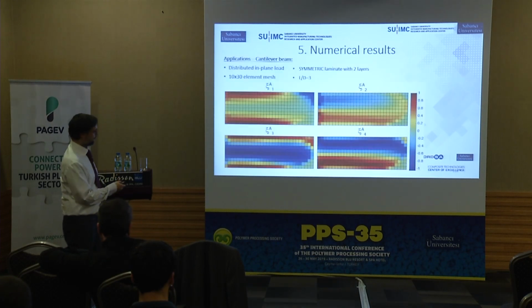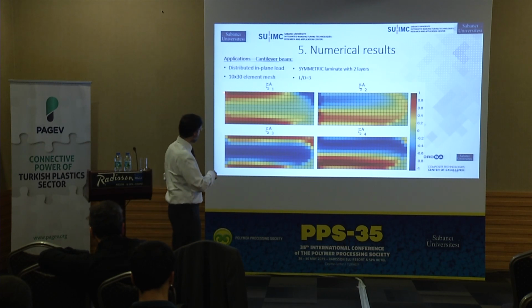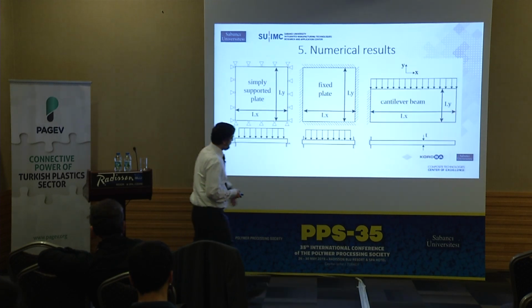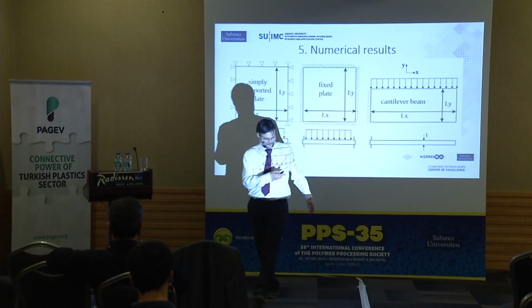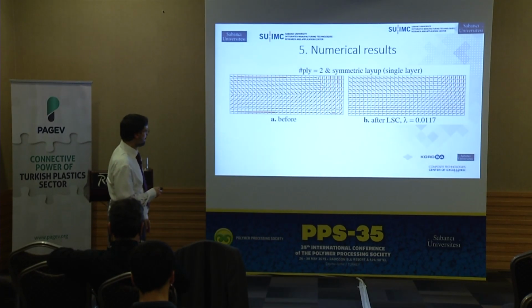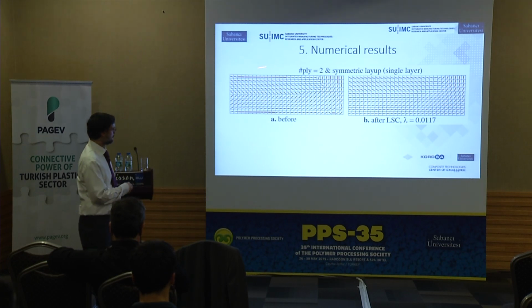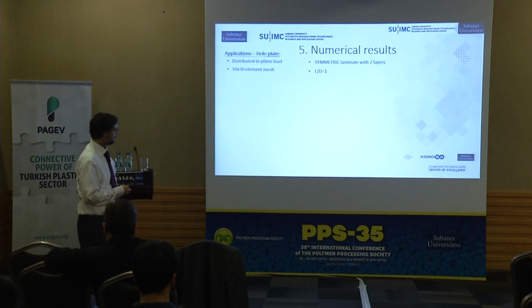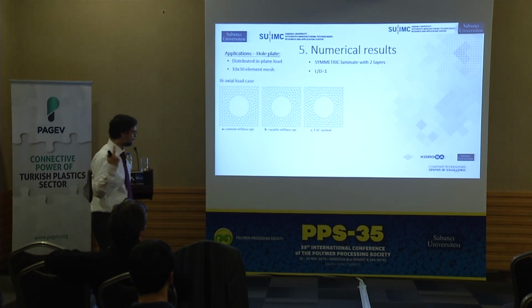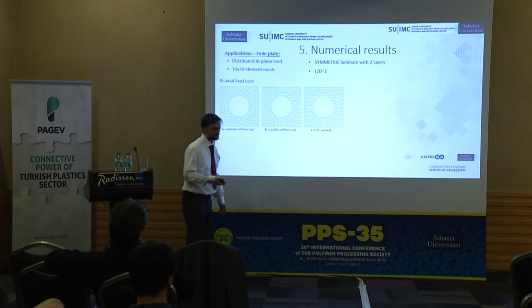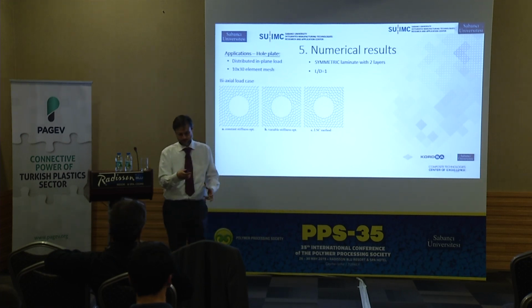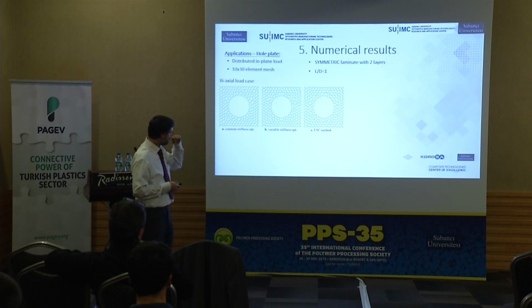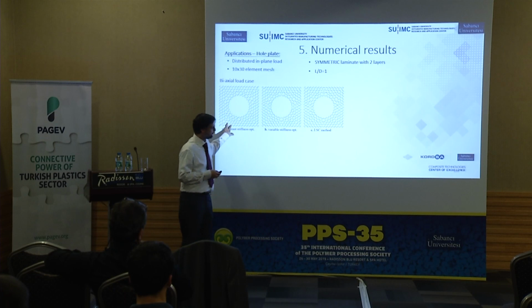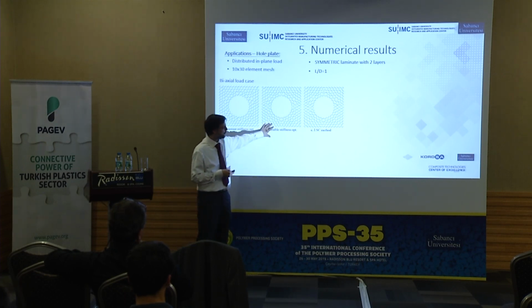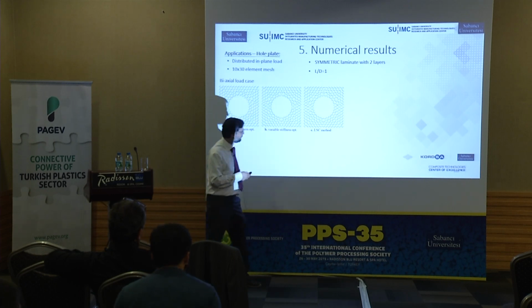And for a cantilever plate, it's not very common to load plates here. Let's say I fix this plate. It's fixed here and load is applied on top of it. So it becomes like this, the optimum solution. And when we apply our method, it becomes like that. Another thing that we recently applied to is an open hole case, where you need some holes in composite materials. This is a biaxial load case. This is the optimum angle distribution we have. And this is when we apply our method here.